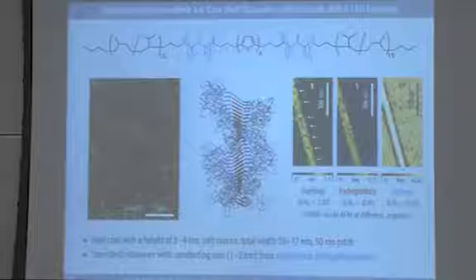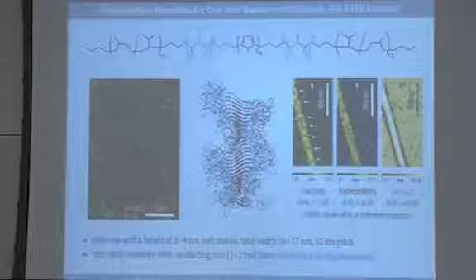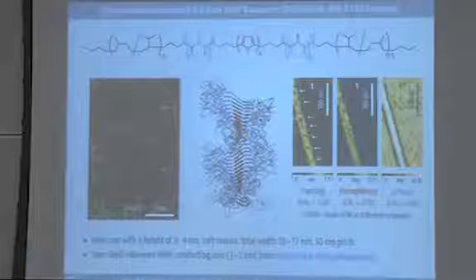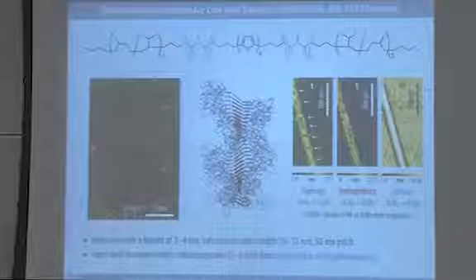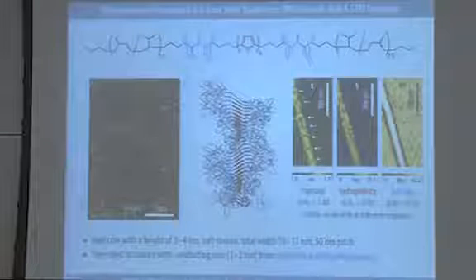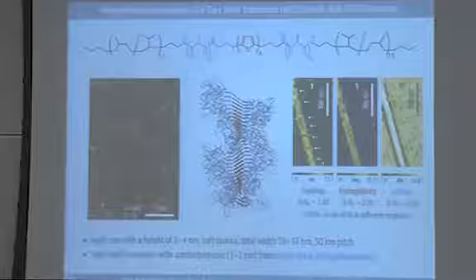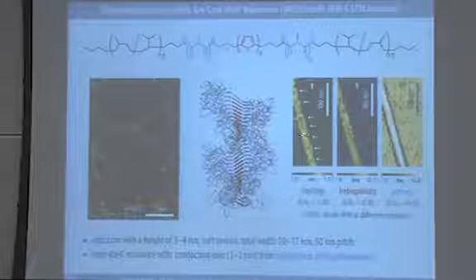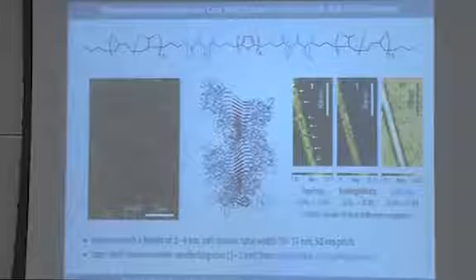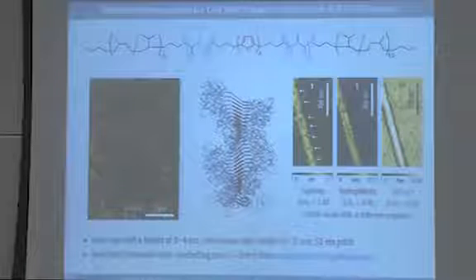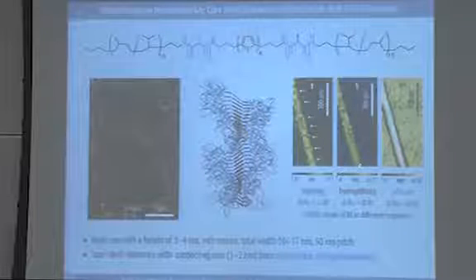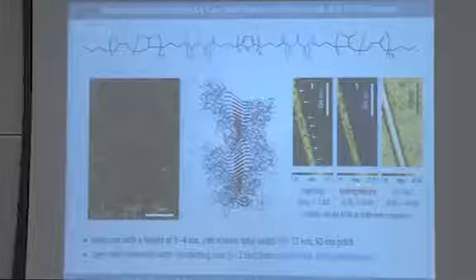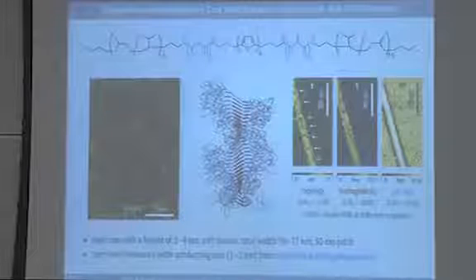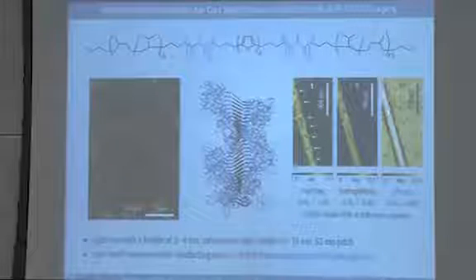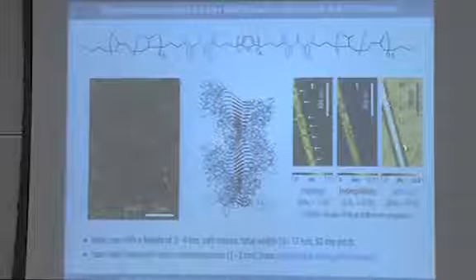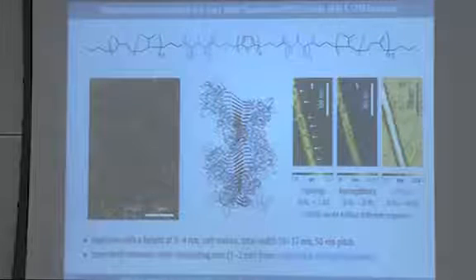And so this allows you to obtain height and phase information at different set points in a single measurement run, so that you're not so much prone to imaging artifacts. And what you can see in these images is that the height image shows you periodic corrugations, which can be attributed to the helicity of the fibrils. In this case, the hydrophilic-hydrophobic contrast doesn't show very much, but the hard-soft contrast shows you that mainly the soft material shown in dark here is actually placed along the flanks of the fibrils.